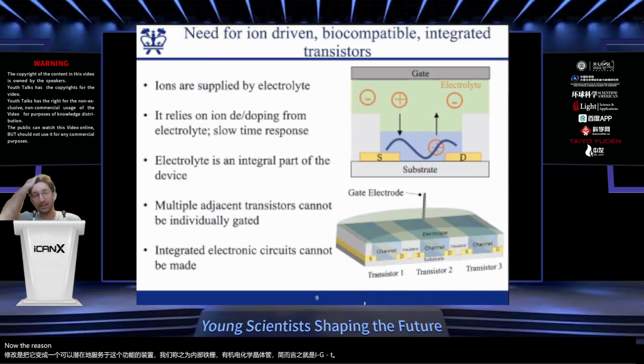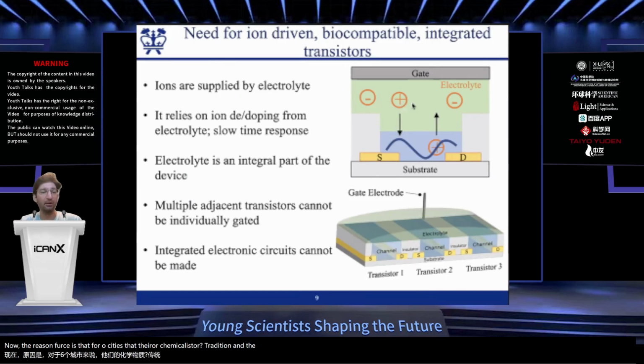Now, the reason for this is that for OECTs, the electrochemical transistors, traditionally the way it operates is that the electrolyte is an integral part of the device, meaning it borrows ions from the electrolyte, and the intake and uptake of ions from the electrolyte causes modulation in the channel. This makes the device quite slow because it relies on the transport of ions from an external electrolyte into the channel. Additionally, because the electrolyte is shared among multiple transistors, it is challenging to individually address each transistor. As a result, gating a specific transistor without crosstalk becomes very challenging.